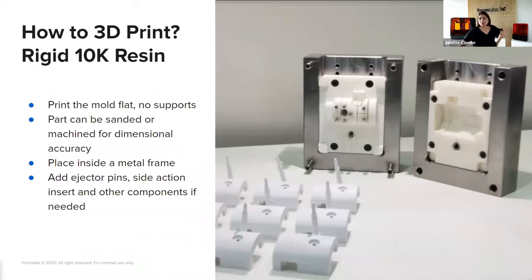As I mentioned before, you can post-treat the mold either by just grinding it with sandpaper to have a perfect flatness, or sandblasting also helps for a good surface finish. This is already a very matte and very smooth surface finish, but there's always some more we can do. You can also follow some recommendations, such as printing the mold flat, not using supports on the molding surfaces. This is very important. If you can avoid that, it will really help to achieve the best quality.